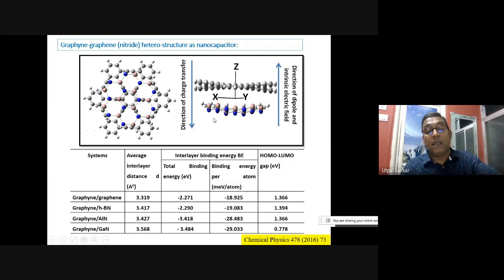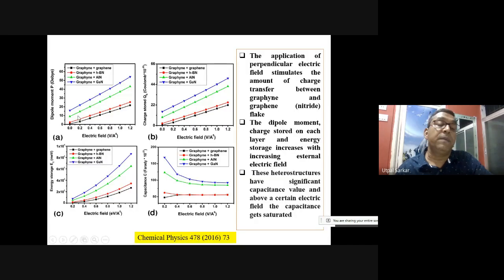For this molecular system, we have calculated the same: the HOMO-LUMO gap, binding energy, and how much capacitance we have. So here it is. The dipole moment is linearly increasing for this system with increasing electric field, and the charge storage between these two is increasing. Here it is the energy storage. Energy storage is quadratic in nature, whereas the charge is basically linear, as we have found in the earlier cases. This is the capacitance.